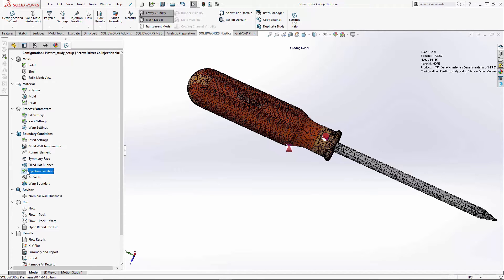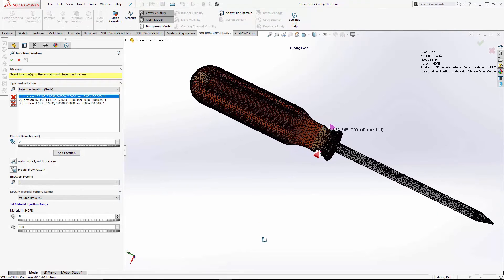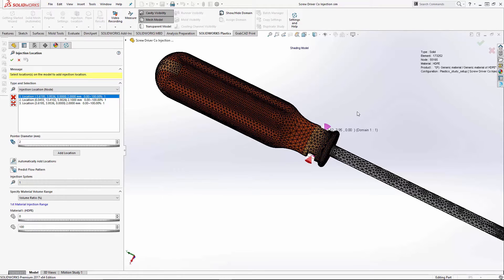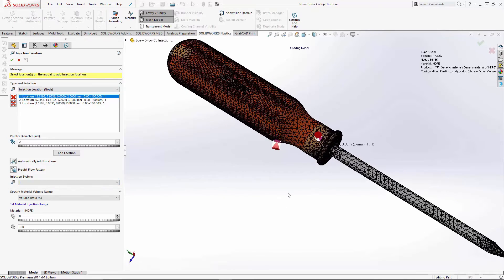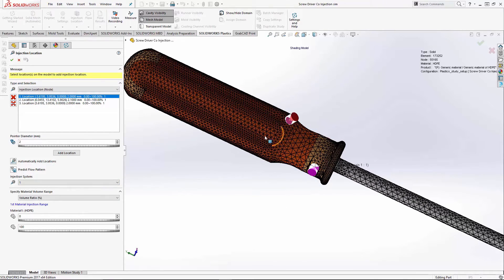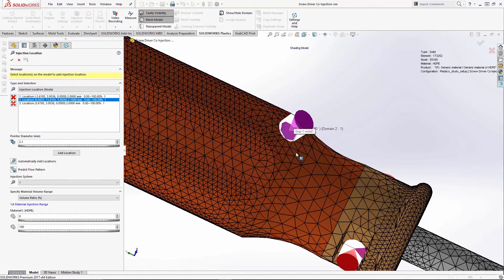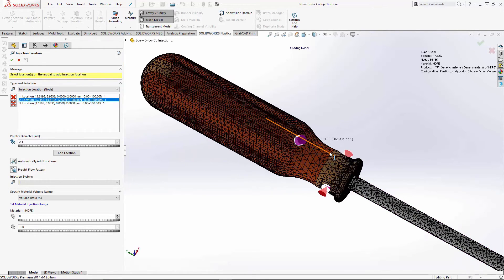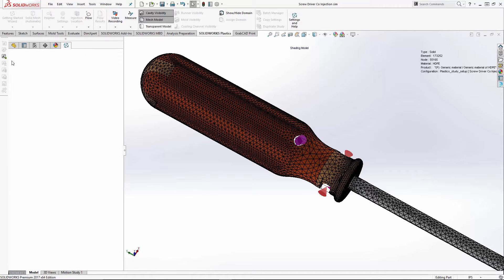Finally, we'll set injection location, which for this part, since it's an insert overmold, I've placed two injection locations on the inner handle. So the material pressure will be equally on both sides of the insert. It won't try to push or bend the insert to one side or the other. I've got both of those set up that way. You'll set your injection location for the outer handle. It automatically sees it's domain two, so it will inject domain two material into it after domain one finishes filling. There's no other settings you really need to change within the injection locations for this process.